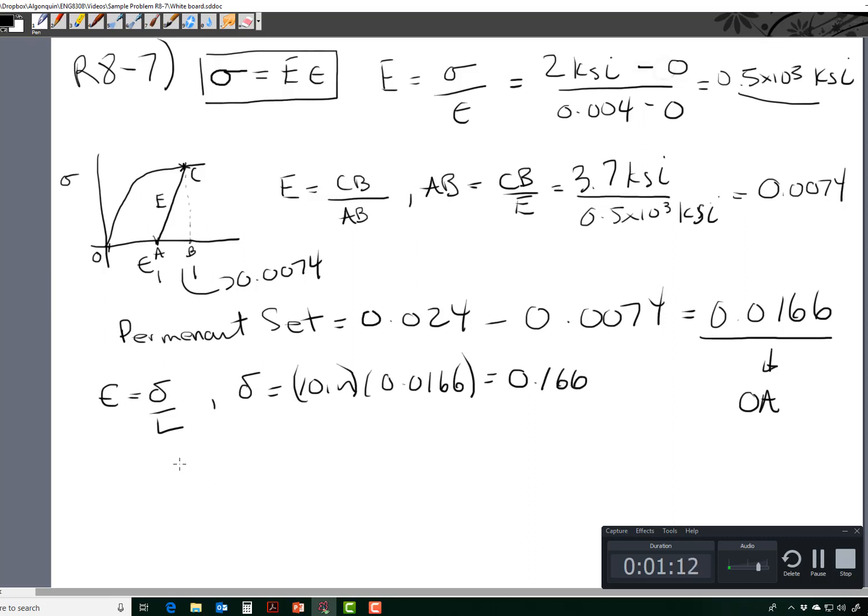So then the new length of our sample, the length is equal to its original length, 10 inches, plus its new elongation, 0.166, which equals 10.166 inches, and that should answer all of the questions.